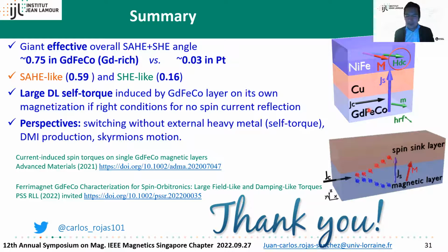I mean, by changing the thickness of gadolinium iron cobalt, we can tune the anisotropy, right? Here in this case, it works the other way from typical magnets, for example with cobalt, where reducing the cobalt thickness changes the magnetization from in-plane to out-of-plane. Here, reducing the thickness of gadolinium iron cobalt, or rare earth transition metal layers, makes it likely that the magnetization falls in-plane. Increasing the thickness makes the perpendicular magnetism more robust.